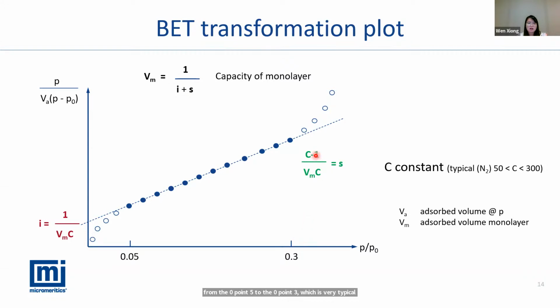The C constant accounts for the adsorption energy of the first layer and the energy of condensation. So in this definition, we have to get a C constant larger than 0 in our BET plot. If the C constant is smaller than 0, your BET plot doesn't make sense. It's invalid data. The stronger the interaction between the gas molecule and the surface, the higher the C value we get.